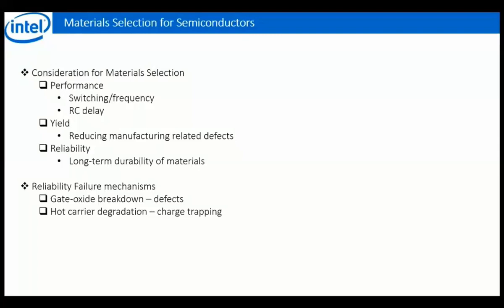And this happens due to defects inside the gate, and we want to decrease those defects as much as we can. The next thing is hot carrier degradation. This happens due to charge trapping, defects like point defects and two-dimensional defects, dislocations and stacking faults. These create the right thermodynamical trap for charges to accumulate, right, and cause various issues inside the semiconductor. So that's a problem. The other one is radiation effects. We have cosmic rays that come from the sky that hit our computers, our CPUs, and that might cause a bit flip.